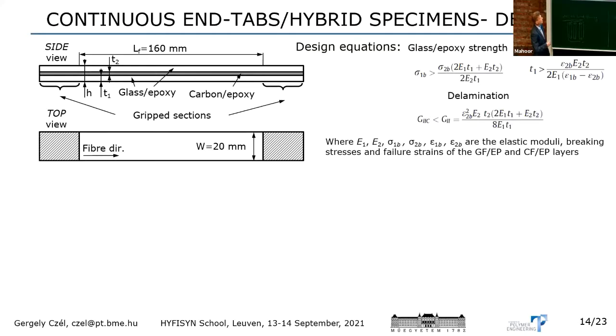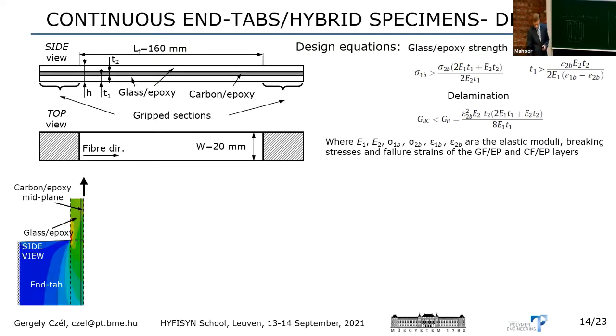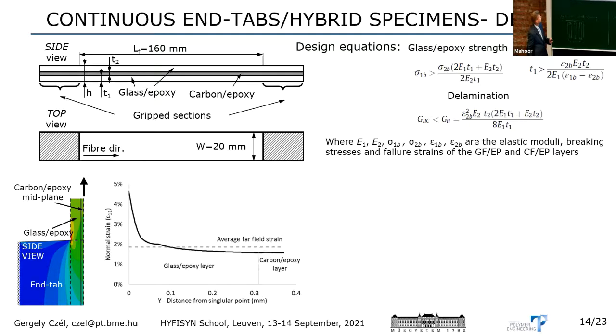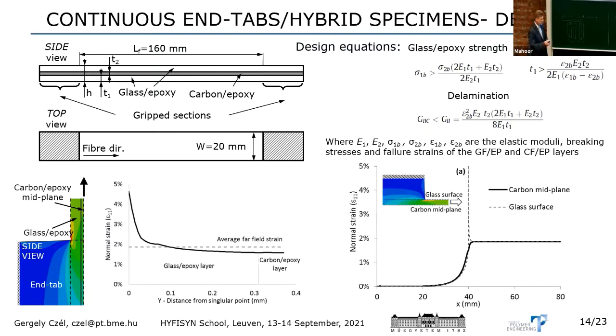We need to make sure that the system will delaminate when we have the first fracture in the carbon layer. So for this, we need to make sure that the energy released at the fracture of the carbon epoxy is higher than the fracture toughness of the interface or the hybrid. And here you can have the annotations for reference. And Jentil already touched on these graphs.